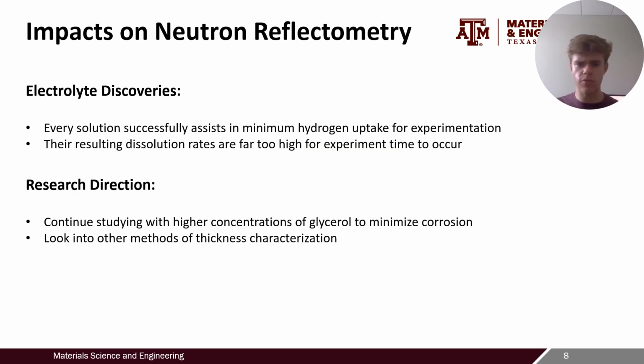So circling all the way back to the main motivation behind this project, I've found that charging nickel in every glycerol-based electrolyte exceeds the necessary level of hydrogen adsorption needed for experimentation with NR. Unfortunately, this does come with the cost that they cause far higher dissolution rates than we can currently work with. So going forward, we have a proposal which we'll be doing the next month on August 28th, and further optimization is clearly necessary for these electrolytes.